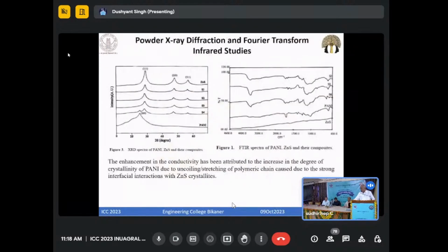Of course these were microscopic, very interesting X-ray diffraction studies. The lower curve is that of polyaniline. You get a broad peak of polyaniline. As you increase the concentration of zinc sulfide, you see the polyaniline peak is disappearing. So zinc sulfide is working as a template for polyaniline, and polyaniline is getting better crystallinity. And because of better crystallinity, it is giving you higher conductivity. So you see, you can increase the conductivity of the material if you know the real physics behind it. This is again a very interesting result we have got.